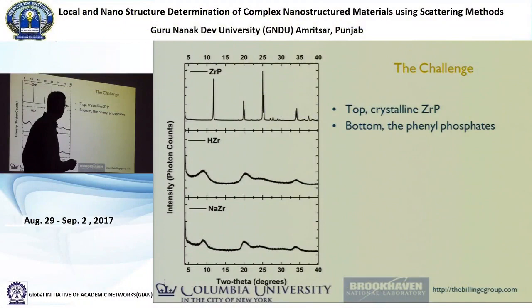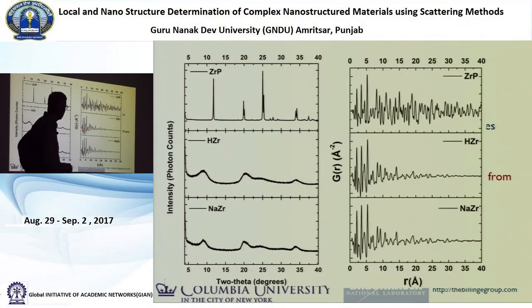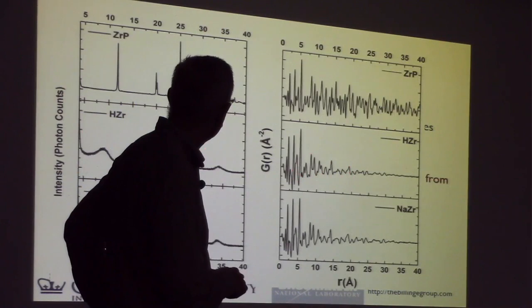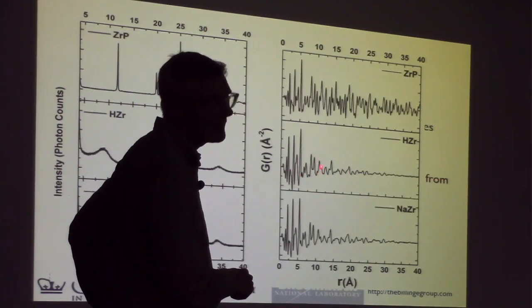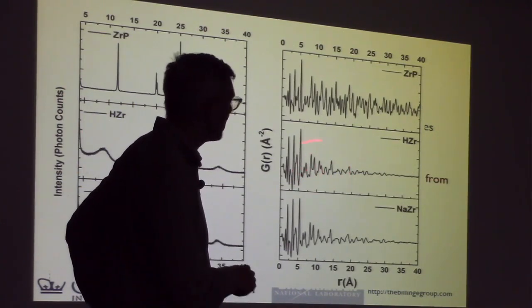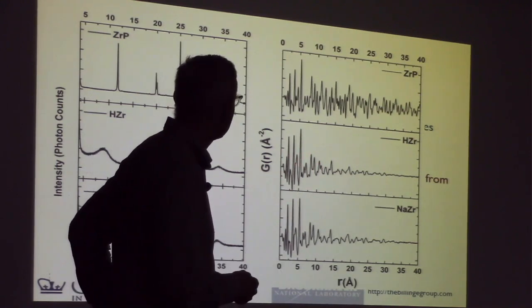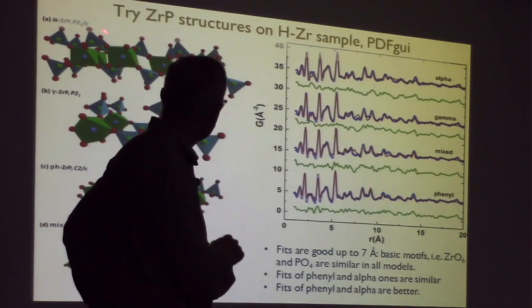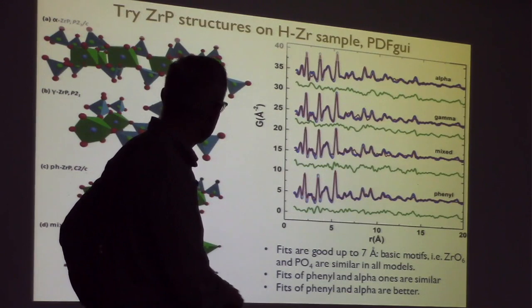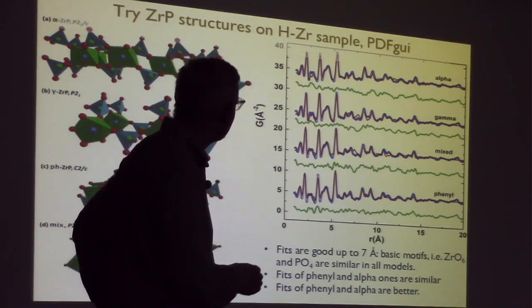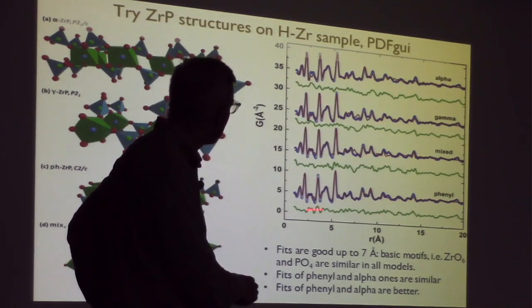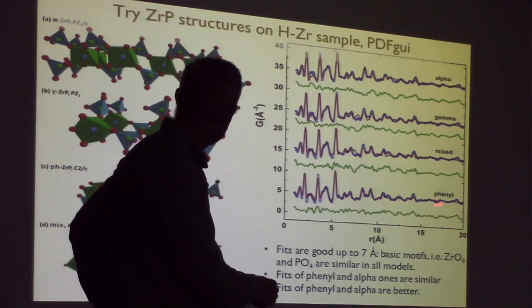But by doing PDF, we do this high Q measurement, and we get data that look like this. So this is a G of r versus r, and we get these beautiful sharp peaks, and it's the same sample as this one, just measured differently. Now we have a lot of information that we can fit to get the structure out. And so we can try different candidate models for what the layers look like. And we can compare them, and actually this one is the one that seems to be fitting best.